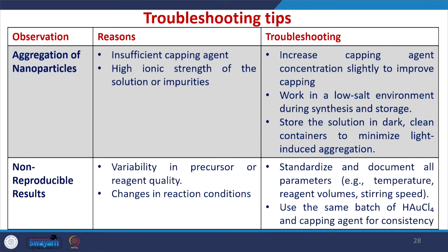Some of the other problems are aggregation of nanoparticles. The aggregation of nanoparticles may happen due to insufficient capping agent, or it may be due to the high ionic strength of the solution or impurities. In this case, you have to increase the capping agent concentration or work in a low salt environment during synthesis and storage, and store the solution in a dark and clean container to minimize light induced aggregation.